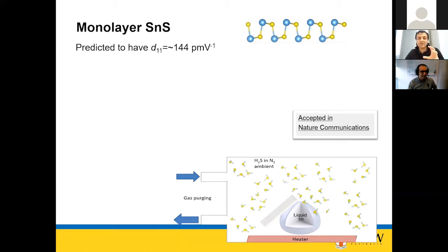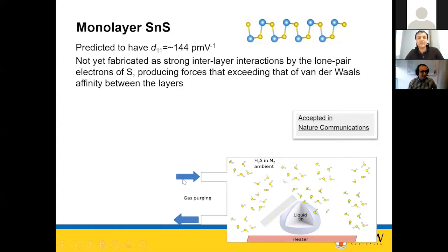That will be extraordinary, and of course, it's a semiconductor with a small band gap. If you make the contacts properly, you can harvest current. A large voltage, a large current. That means just by bending, you can produce power. Okay, going back to how to produce it, we change the ambient from oxygen to hydrogen sulfide in a glove box, and we harvested the surface layer, tin oxide, no, tin sulfide this time.